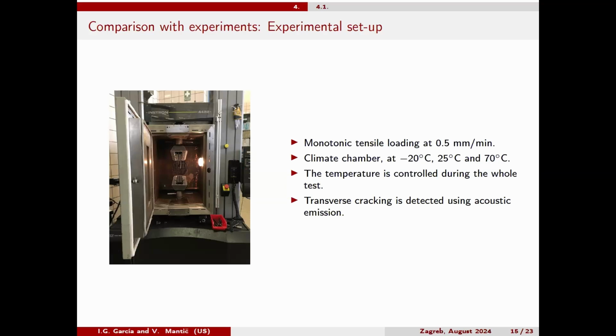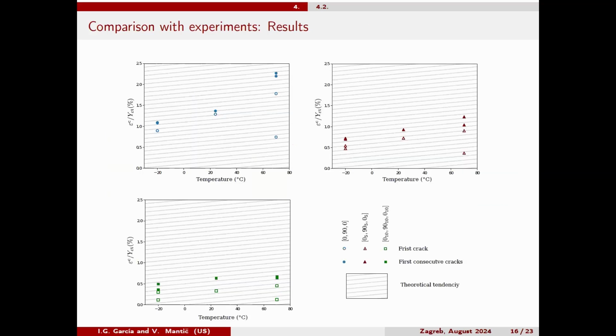So we tested our specimens at these 3 temperatures. Of course, we control the temperature and we detect the transverse cracking with acoustic emission. That is the classical method used in this kind of experiments. So these are the preliminary experimental results that we obtained.